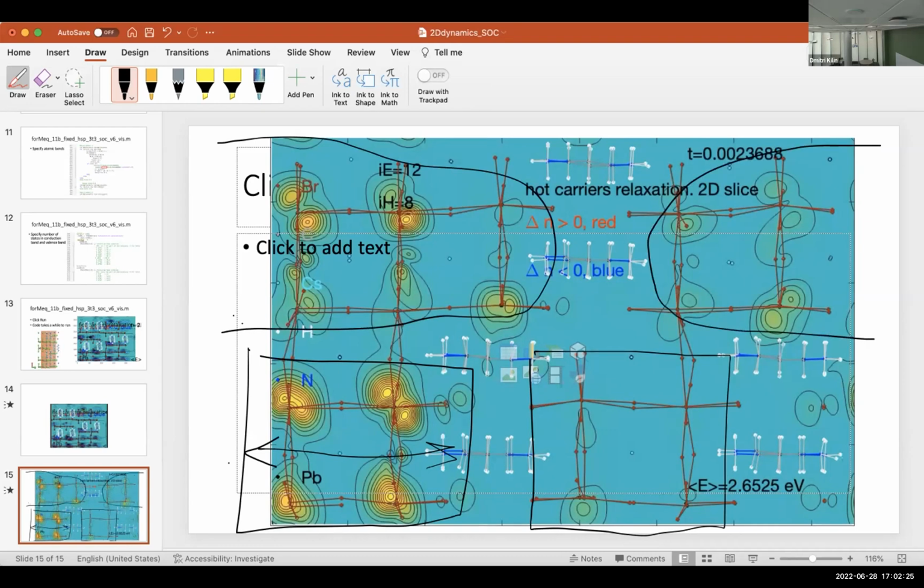And this thin film with 2 layers and 5 layers do have different regimes of quantum confinement. The gap in the thinner one is bigger than in the thicker one. So it is expected that both electron and hole will migrate from a more confined to a less confined region.